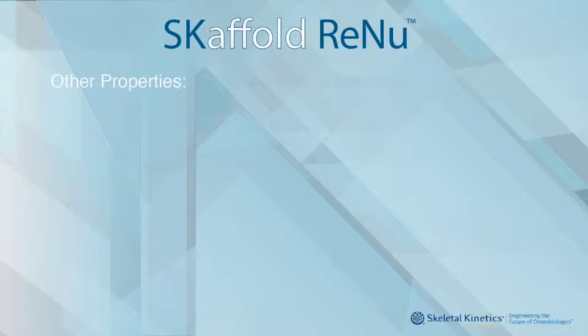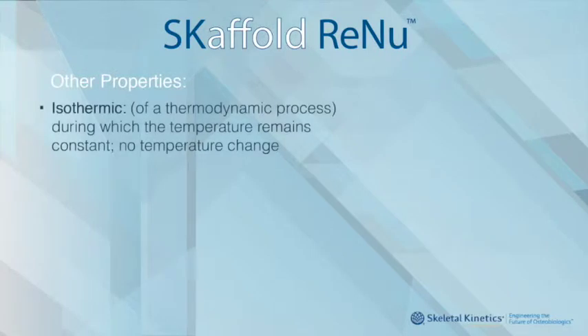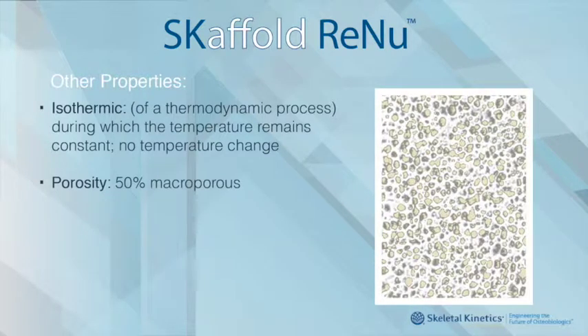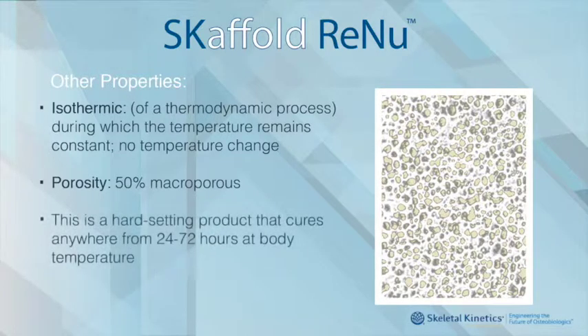Other properties of this unique combination graft include it is isothermic, during which the temperature remains constant. There is no temperature change in this graft. Porosity is 50% macroporous, a very unique porosity. The picture on the right of the screen offers an example of what this graft might look like in a magnified image. This is a hard-setting product that cures anywhere from 1 to 3 days, or 24 to 72 hours. And, as a note, it is not adhesive.